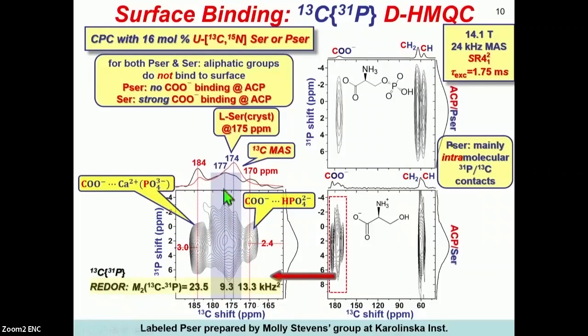The group in the middle here, marked by the blue rectangle, is attributed to carboxy groups that do not bind directly at the surface, as opposed to the other two groups here, which we have made tentative assignments of based on the chemical shifts. So for instance, the peak here at 184 ppm, we attribute to carboxy sites that are bound electrostatically to calcium ions at the surface. And those calcium ions are mainly surrounded by non-protonated phosphate groups. The other peak over here, which has a lower chemical shift of 170 ppm, also correlates with phosphates with lower phosphorus shifts. This peak we attribute to hydrogen bonding between the carboxy group and HPO4 groups.